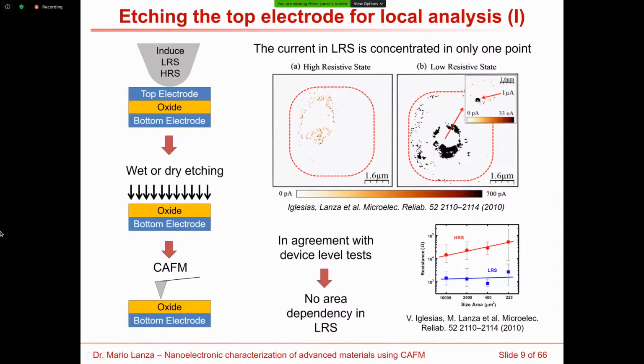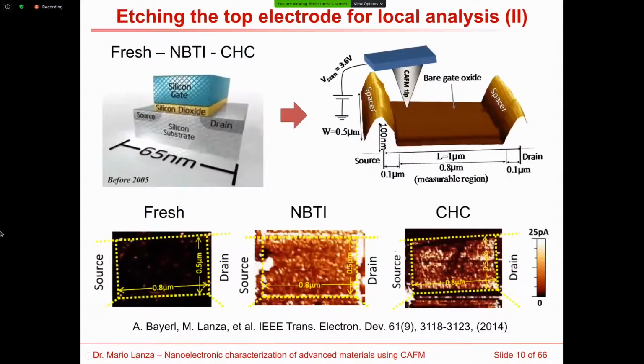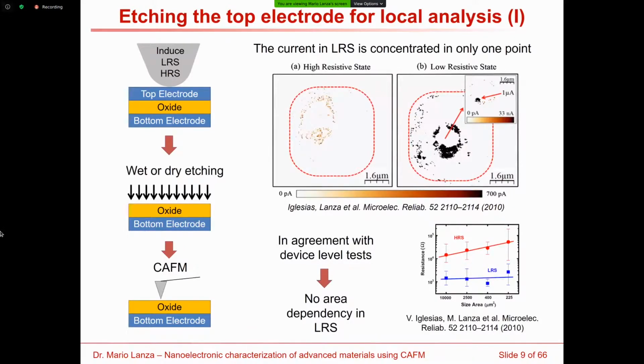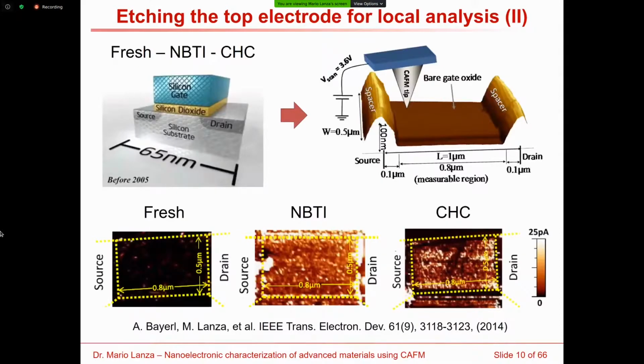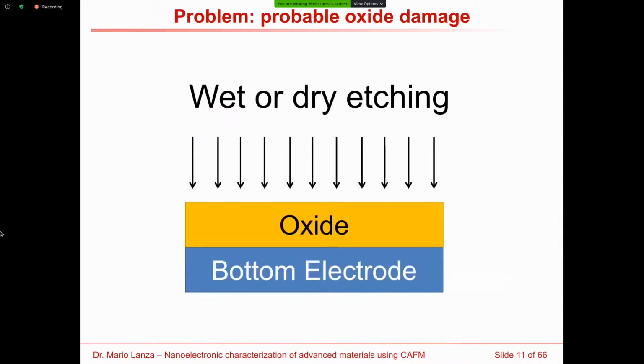This method can also be used to analyze, for example, degradation of field effect transistors. Here in this work, we perform a similar study in which we stress one field effect transistor with NBTI and with channel hot carriers, and after that we etch the top gate and we scan the surface of the dielectric on the channel with the conductive AFM, and we could find some interesting differences. However, this technique has one problem, which is that the etching could damage the surface of the oxide because the selectivity of the method maybe is not perfect, and you can damage a little bit the surface of this oxide.